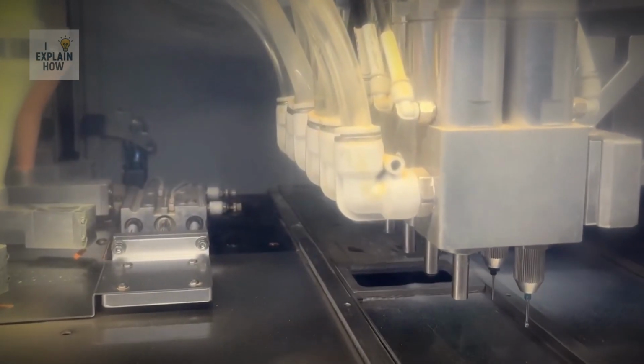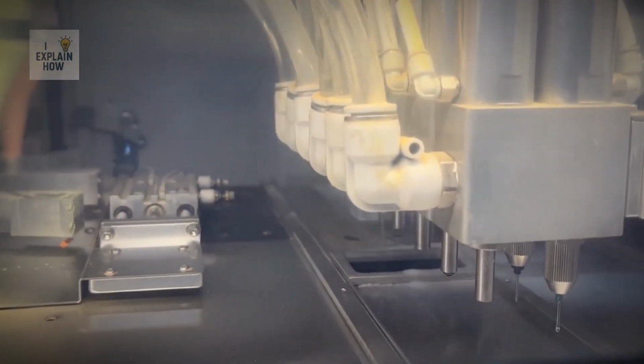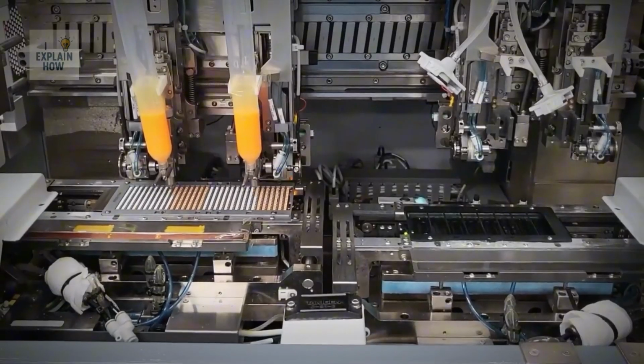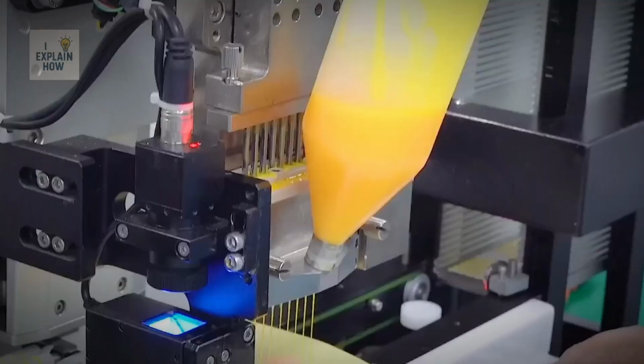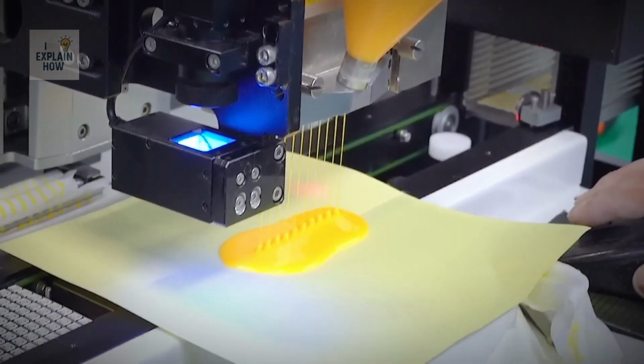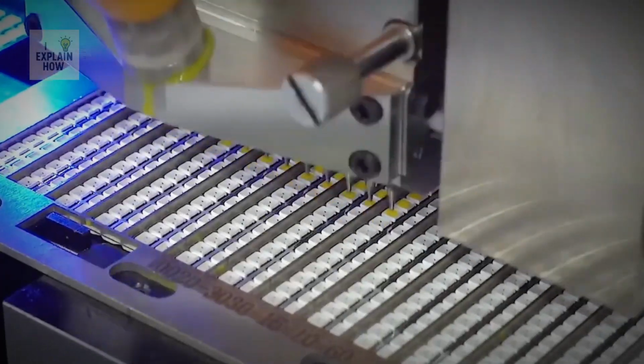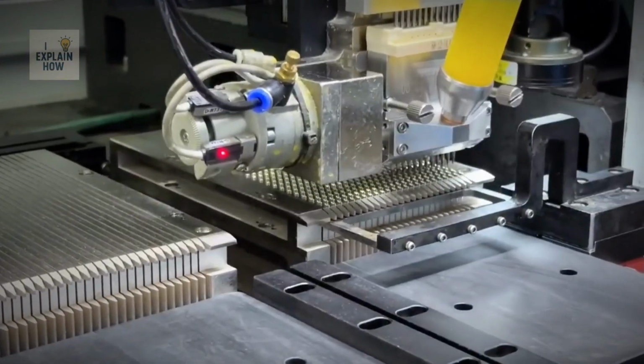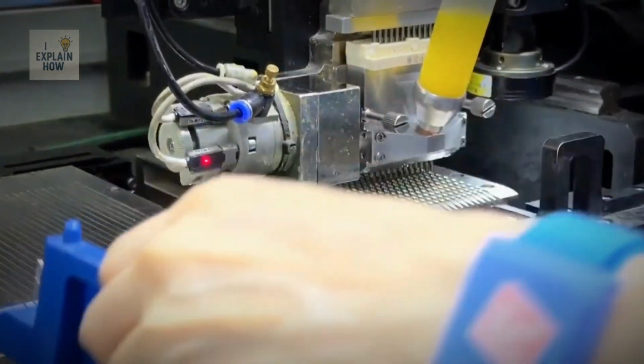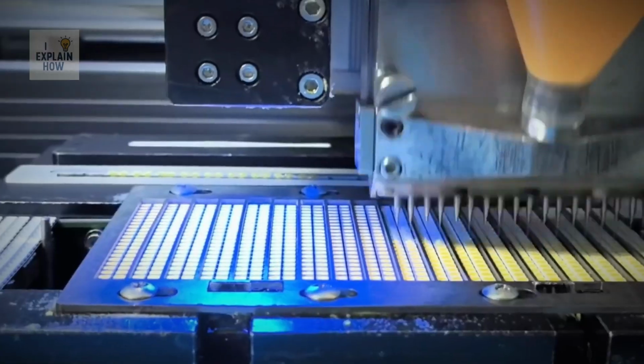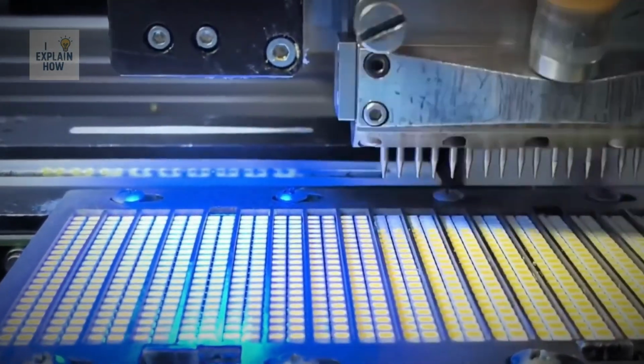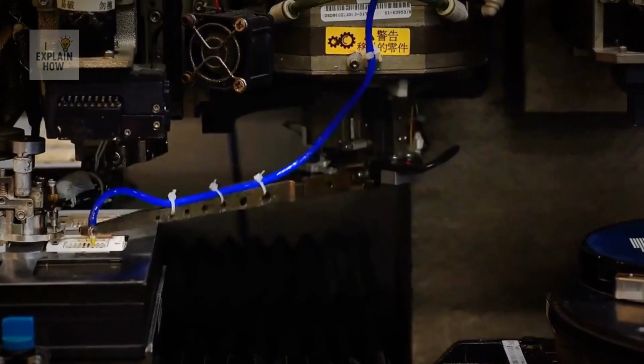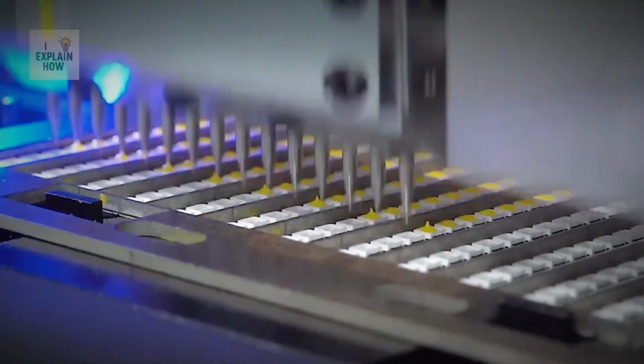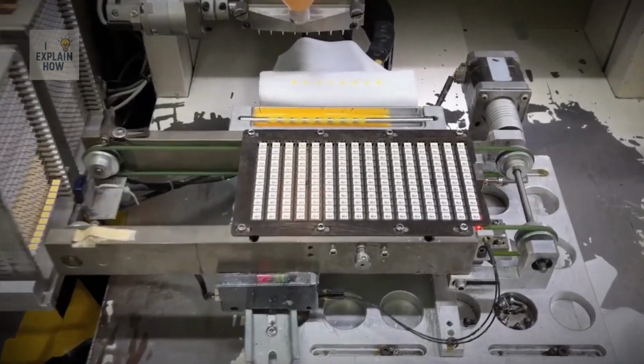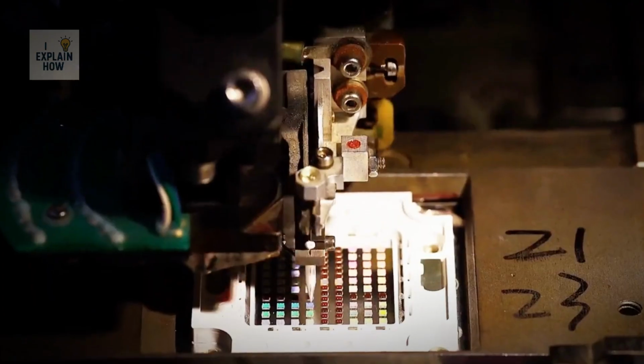Thousands of LEDs mounted on LED frames are fed into the machine chamber, where ultra-fine dispensing needles deposit an extremely consistent volume of the mixture onto each individual LED chip. This thin coating is responsible for converting the chip's native blue light into the white or amber light visible to the human eye. Once coating is complete, the entire LED tray is placed in a curing oven operating at approximately 150 degrees Celsius. At this controlled temperature, the epoxy fully hardens, permanently locking the phosphor layer in place.